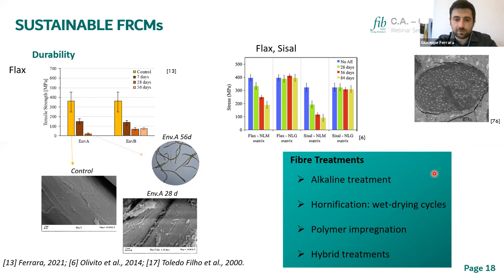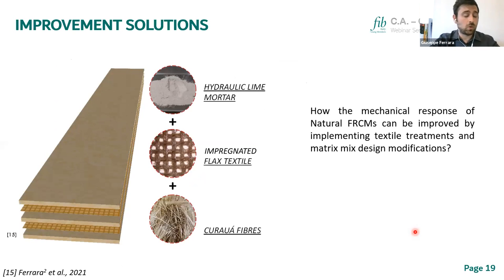So some fiber treatments exist to improve this durability aspect, for example alkaline treatment and wet-drying cycles, which are pretty effective for improving both strength and durability, and polymer impregnation, especially the last one. It's very important because it can create an isolation of the fibers from the matrix. At the same time, it can also improve the adherence between the two materials and the stiffness of the fibers. So in the last part of my presentation I would like to show some work I've done in the last years, aiming to see how the mechanical response of natural FRCMs can be improved by implementing some textile treatments or matrix mix design modifications.